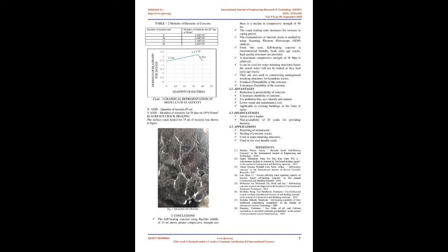When cracks appear in the concrete, water seeps into the cracks. The spores of the bacteria start to grow, germinate, and feed on the calcium lactate, consuming oxygen. Insoluble limestone is converted from the soluble calcium lactate. The insoluble limestone starts to harden, thus filling the crack automatically without any external requirements.